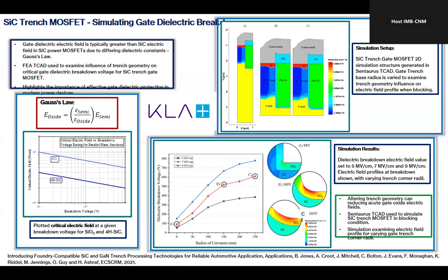So we did that here, and this is simulation work initially. For a higher radius of curvature, at different high field points in the semiconductor, you can see the effect that has on the breakdown voltage. And the higher the field, the bigger the effect. So it was really important. The conclusion from this is that it's really important to have a nice rounded edge there to relax the field in the oxide, even without these additional structures around the corner. On the left here you see that's just this equation implemented for different breakdown voltage in silicon carbide, and you see that's roughly 3 times that value in the silicon dioxide.